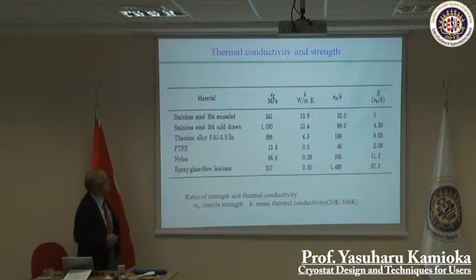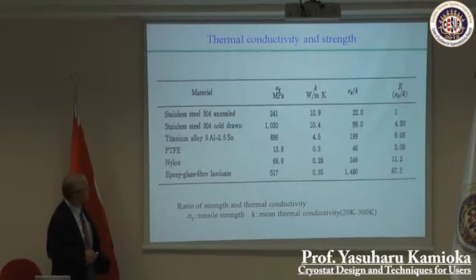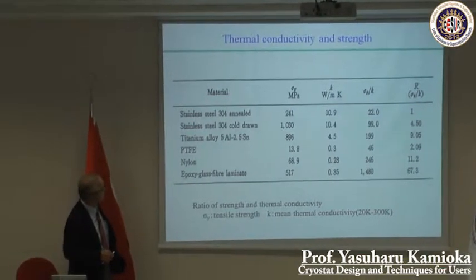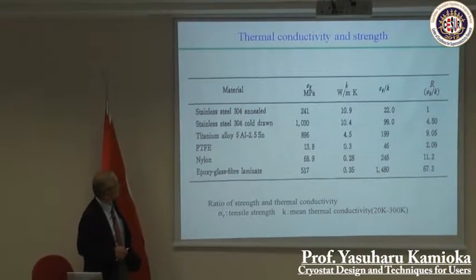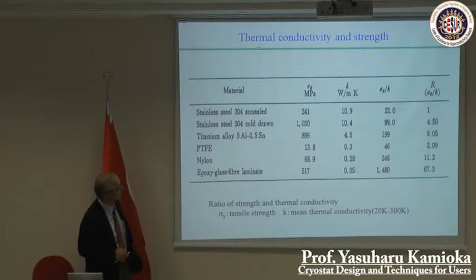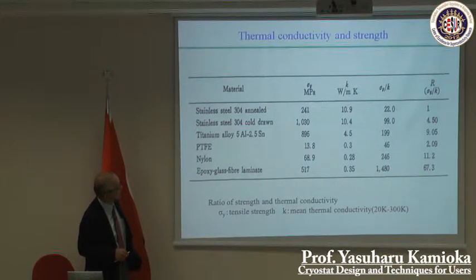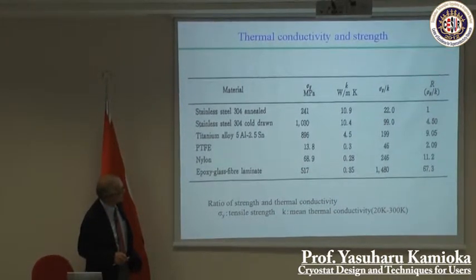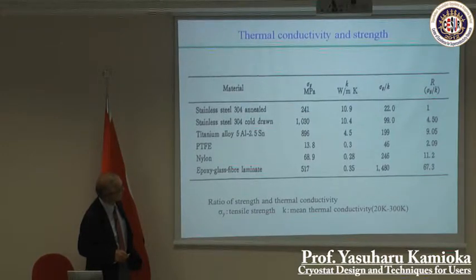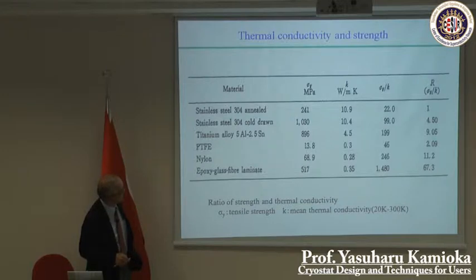One shows thermal conductivity and strength. The toughest material we use is stainless steel 304, cold drawn type, and strength is this number. And thermal conductivity is here. Strength divided by thermal conductivity is 99. And when this number is 1, then stainless steel is 4.5.